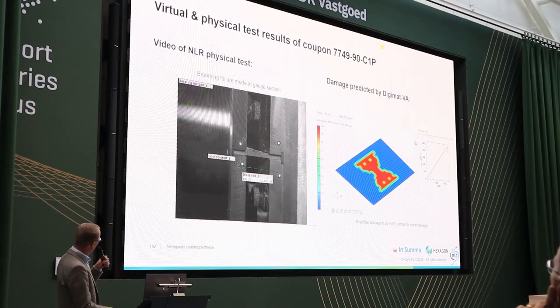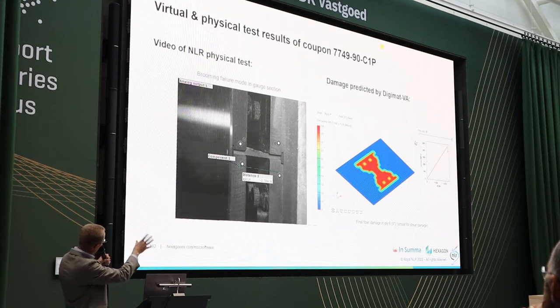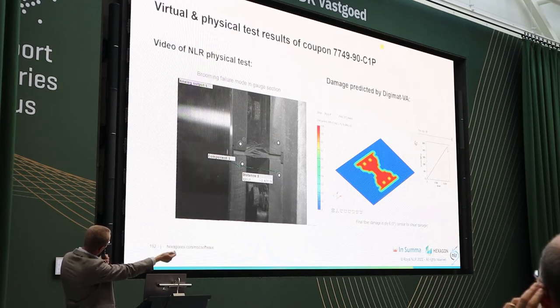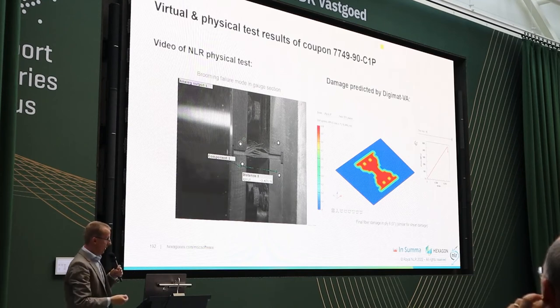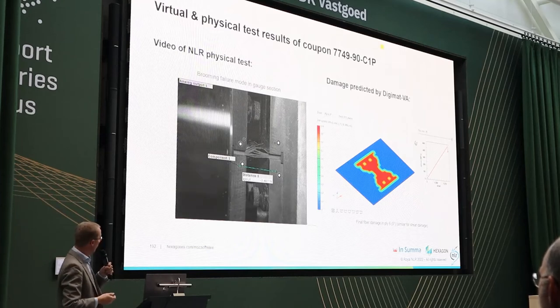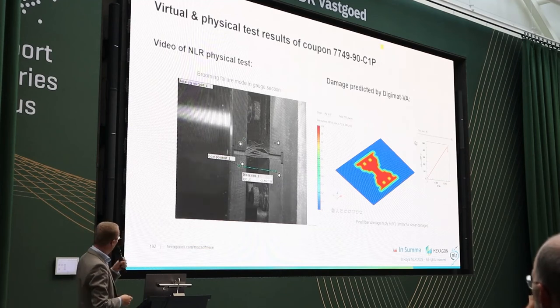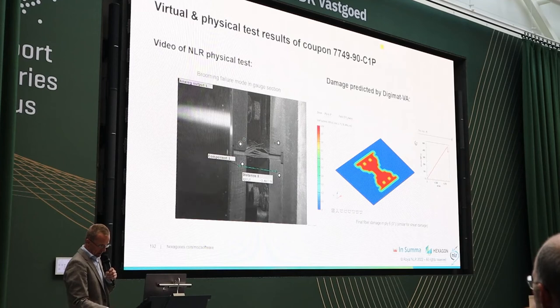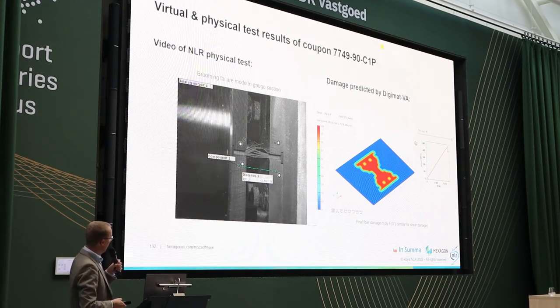It's moving. Okay, we have to wait a couple of seconds. In the physical test, the coupon is rotated 90 degrees, and the top platen of the bench will compress the component. You see a failure. There are all kinds of things happening: fiber crushing, matrix failing in compression, shear damage, delaminations, all together. So it's quite an explosion. But with Digimat, you can also look into each ply, what kind of damage it is, and see a picture of the zero degree ply somewhere near the middle of the coupon. And you can look at the compressive stress versus strain.